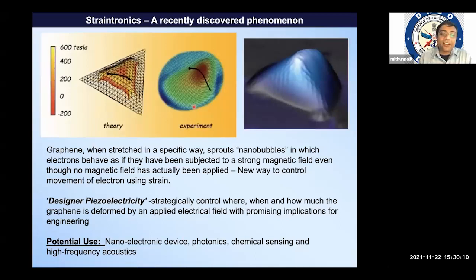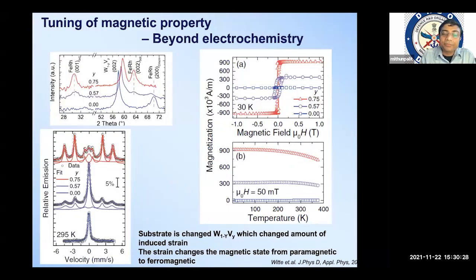So with all this, we are also now trying to explore how strain can be utilized. So it is not only the electric charge, the lithium ion or any other electricity. We can also make use of strain to make the material smart or change the property of the material. This is one paper from the literature. You can see it's a thin film, where they have grown a ferromagnetic iron rhodium film on a tungsten substrate, and they have systematically doped the tungsten with vanadium to change the lattice parameter, producing different stress levels in the iron rhodium ferromagnetic layer.